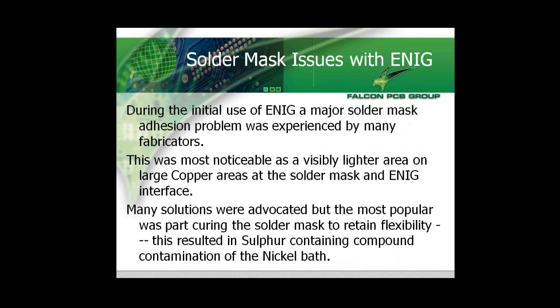During the initial use of Electroless Nickel Immersion Gold, in particular in my recollection throughout the UK, there were many problems experienced by most of the fabricators. This was basically an attack of the hot nickel solution, which started to attack the edges of the solder mask and started to break the adhesion. There were many solutions advocated, but what we found was the most popular one, and this was touched on by Nigel, that we part cured the solder mask and then we performed the Electroless Nickel Immersion Gold and then we fully cured the solder mask.